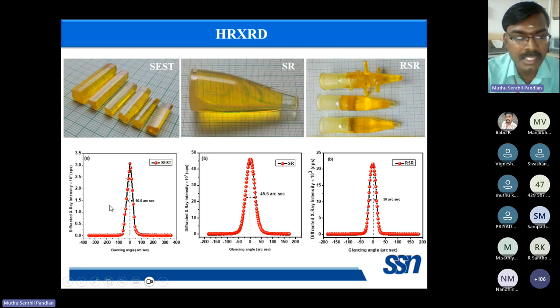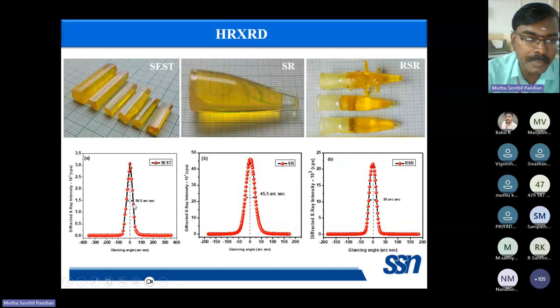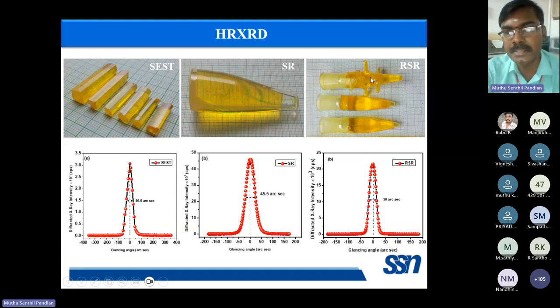But in the case of the conventional method, the grown crystal has a large number of microcracks, is milky and opaque, and has more dislocation density and more growth center boundaries. The FWHM is very high. So very high FWHM in the conventional case, and very low FWHM in the RSR case, which clearly indicates that the crystalline perfection of this RSR method grown crystal is very high and superior compared to the conventional SR method grown crystal.